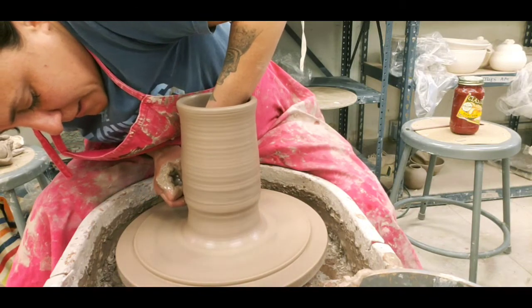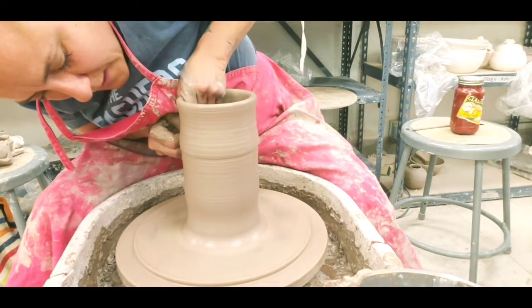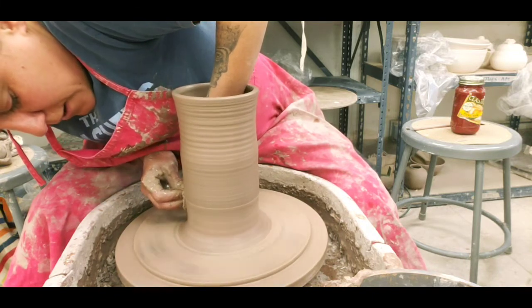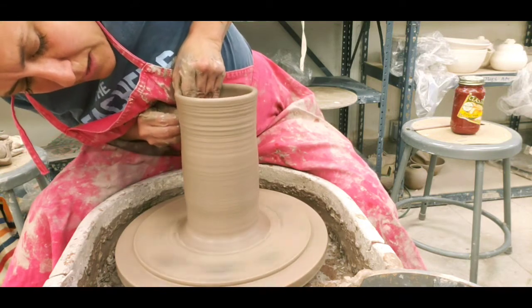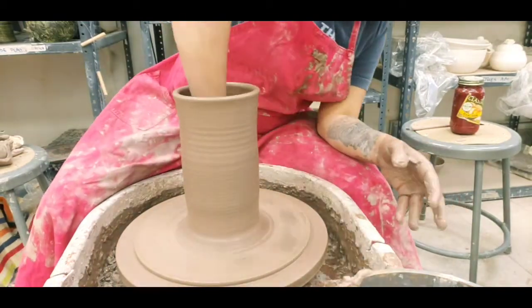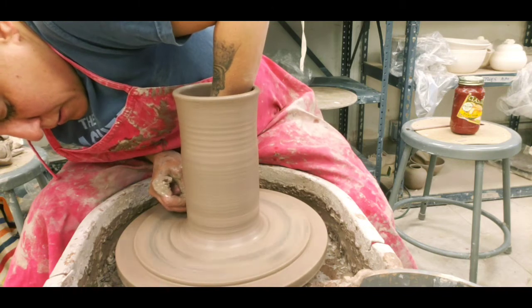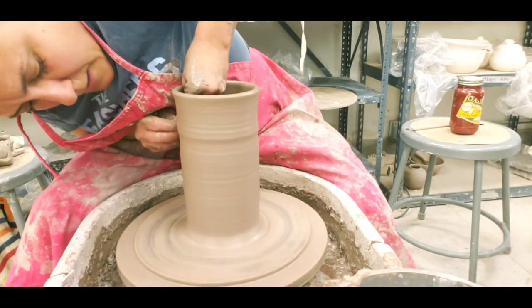This is a light brown speckle clay — it does not fire this color. The first firing, the bisque fire, presented itself to be a slightly pinkish color, but that's not the end result; that's only at 1900 degrees. We're aiming for the second firing to go up to 2300 degrees, and when it goes up to 2300 degrees it becomes a nice creamy off-white color with little brown speckles on it. For potters out there who know about glazes, we find it really hard to use the Amaco glazes with the speckled clay — we get a lot of pocking and pinholing, especially with Obsidian and a few other ones. Let us know, comment or send us a message — tell us what you think the solution might be.